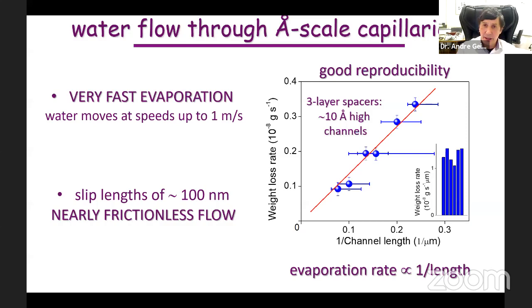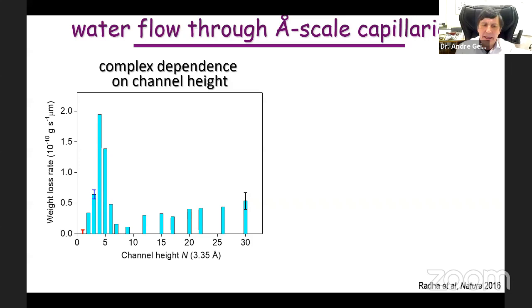I don't want to pretend that we understand everything about those capillaries. When we study weight loss, how fast it flows versus capillary height, in this case shown in the number of spacer layers, it seems to be quite a reasonable dependence. The higher the channel, the quicker the evaporation happens. This is what you expect, but then at angstrom scale, when capillaries become of the order of 1 nanometer, we see a huge enhancement before everything disappears, the flow disappears.